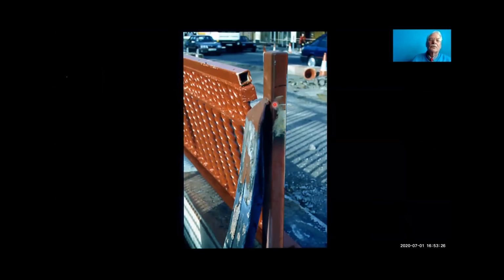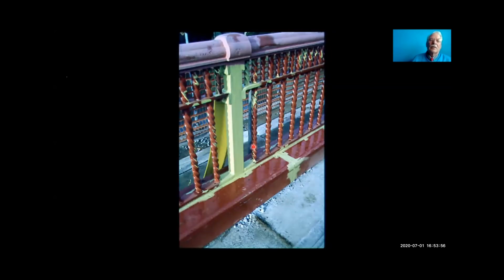And then between the posts, we put another steel rail running right along, welded that on, and then put the original material in again, which was simply cosmetic. The strength is in the new post, the new rail, and the backstay. So that now becomes a clear modern structure made of modern materials, if you like, which is determinate. A structural engineer can calculate the strength of it, and all the original material becomes redundant.